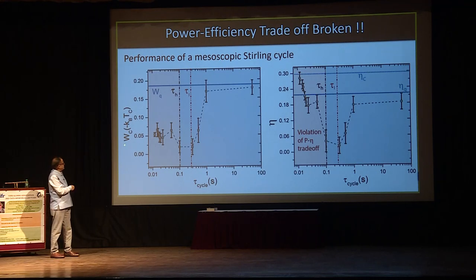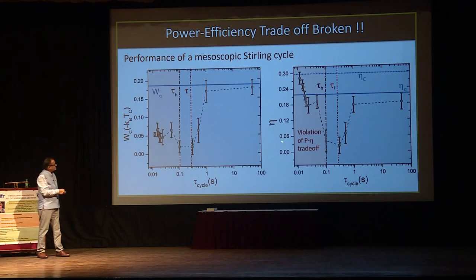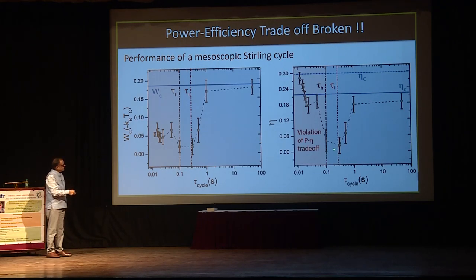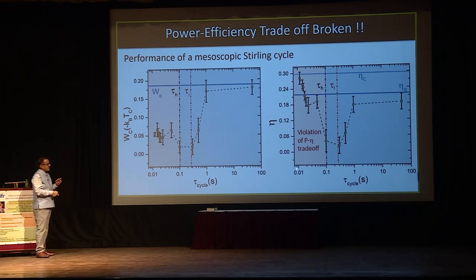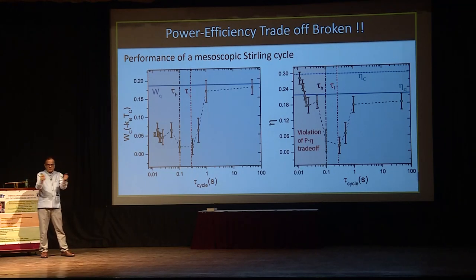Efficiency, if you plot, which is the work done divided by the heat input, Q hot, you can see this is the normal expectation, decrease. But now here, actually, because the tau is becoming small, it exceeds even the Carnot limit, or it reaches the Carnot limit. So here you have a situation at small cycle time, which is what you would ideally like. You want to have a fast engine. Instead of becoming stalled, instead of not working, it is giving you a large efficiency and finite work done.